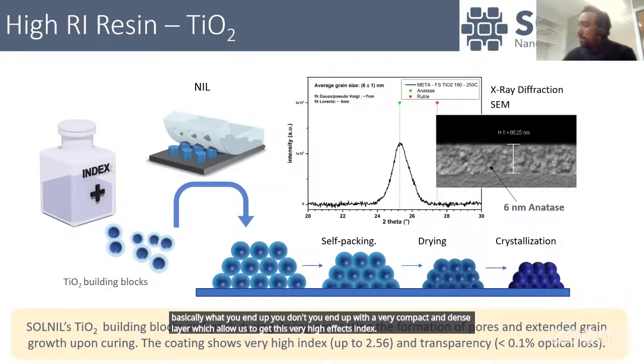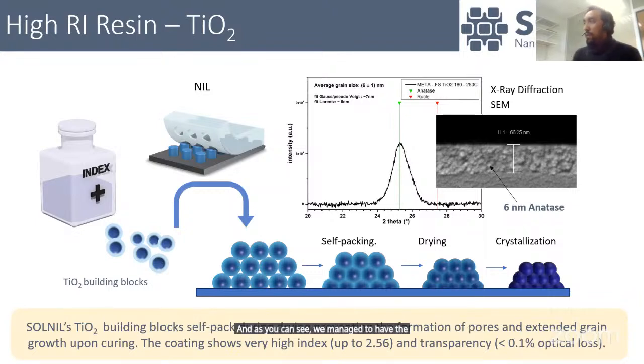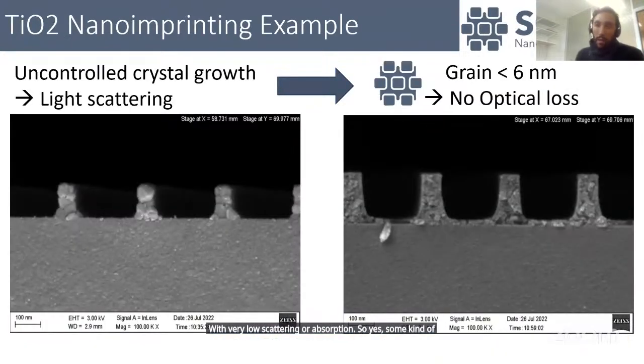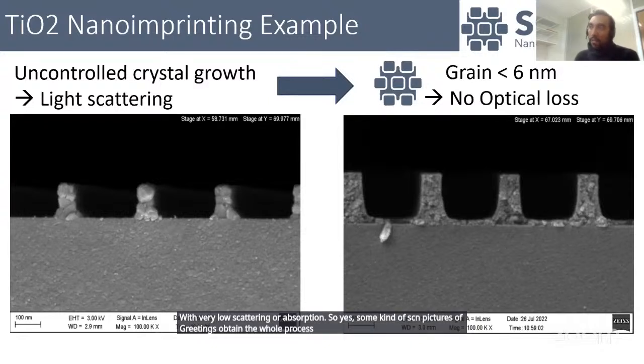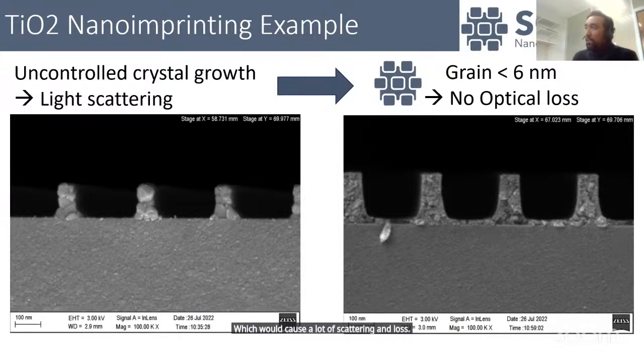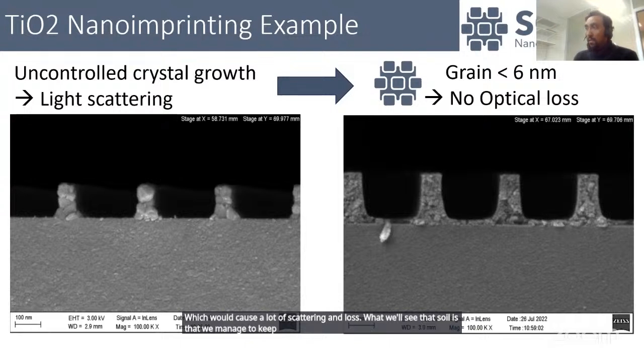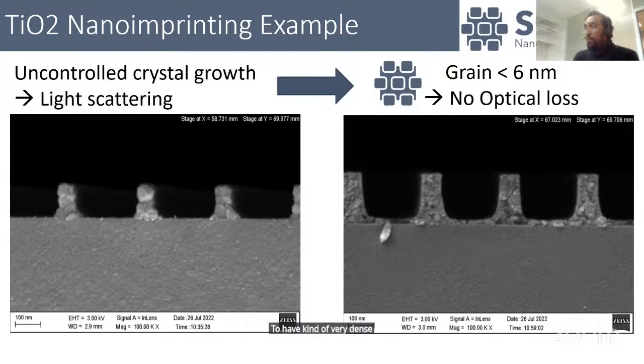And as you can see, we managed to have very small crystal grains, which is why we managed to obtain, even for very high refractive index, very low scattering or absorption. Here are some SEM pictures of gratings we obtained with our process. On the left is standard sol-gel, which is not controlled. If you don't control the crystallization, you end up with very big crystals, like you see on the left, which will cause a lot of scattering and loss. What we achieve at Sol-nil is that we managed to control this crystal growth to have a very dense layer with no scattering, by keeping the crystals below 6 nanometer. This is the key to achieve the refractive index and optical quality.